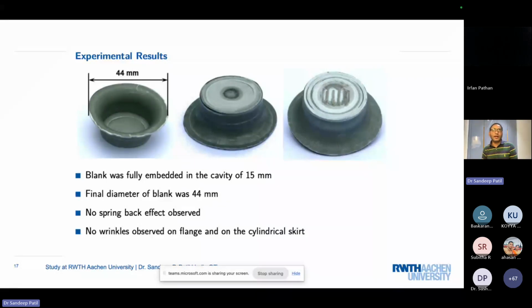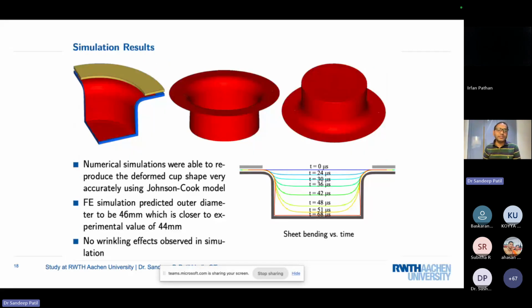So what we did, we checked the experiments, of course, 54 diameter to 44 diameter. We can see nice shapes, as well as some embossing at the end, and we see no spring back effect, no wrinkles observed on the flange and cylindrical skirt. So therefore it was perfect with the experiment. Now we carried out the simulation and found that the outer diameter wasn't exactly 44, but it was 46, which was pretty close.